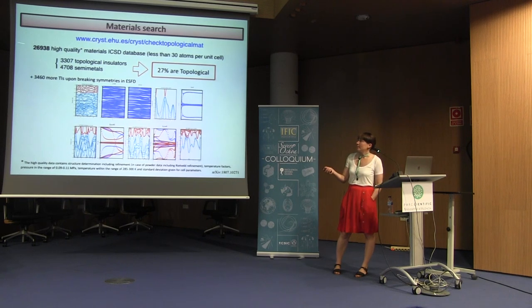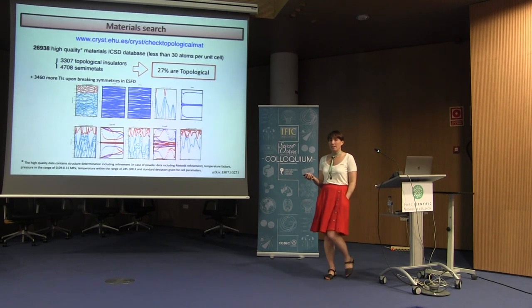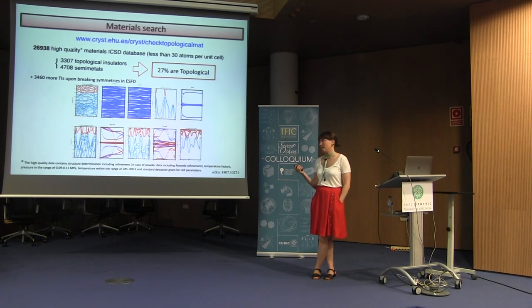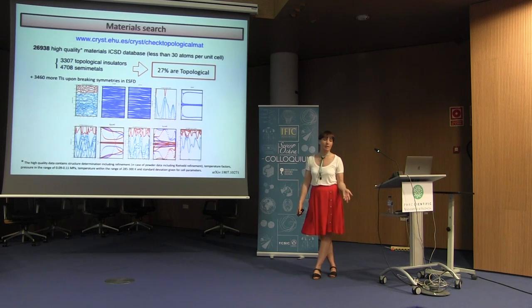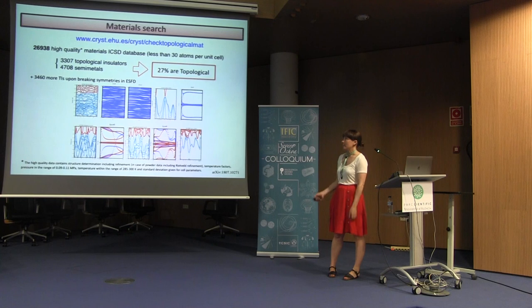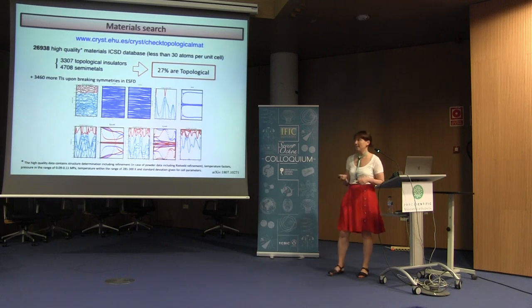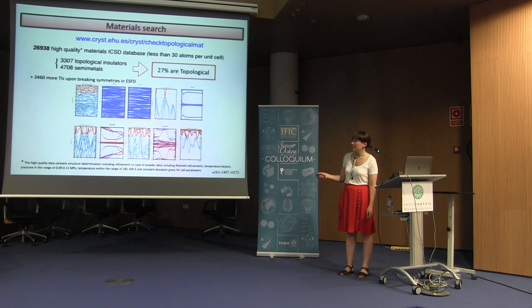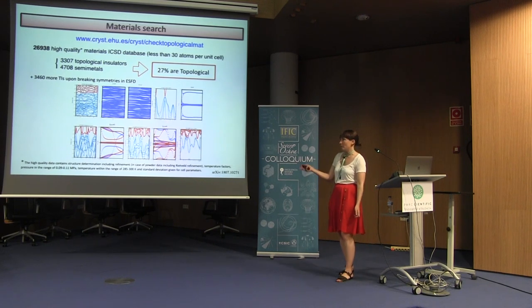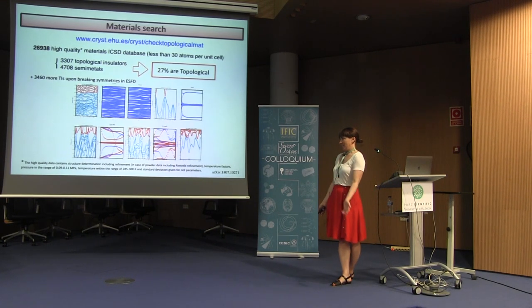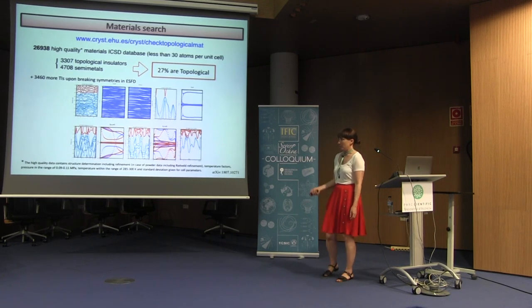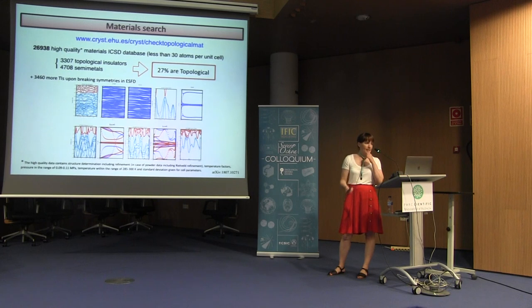So since we look at 26,000 materials, almost 27,000 materials, what we found is like 7,500 materials are topological. Then of course, from theory to experiment, there is a long way and we need to consider some other interactions, but at least in the non-interacting picture, there are more topological materials than we expected. And what we see here are some band structures, and this is the complicated calculation of the Berry curvature that I introduced before, where we take some materials in a space group where topological properties were not reported before, and actually with the traditional method, they are topological.